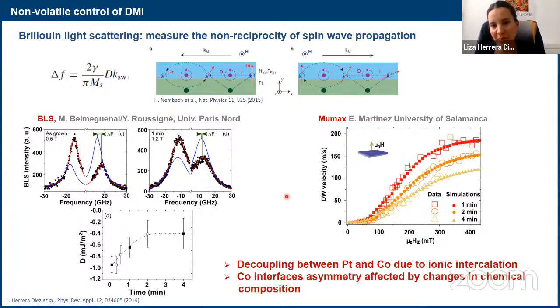So what can we learn from this? Well, we're introducing ions into the system. There is the part about oxidation that is very much related to the perpendicular anisotropy. But if the ions go deeper into the layer, and if they intercalate between the cobalt and the platinum, there's a high chance that we will be losing the coupling between the cobalt and the platinum. And then that can only decrease DMI. And this is really why we think that the DMI is only decreasing as we put more and more oxygen inside. So, well, I wanted to talk to you now about another system.